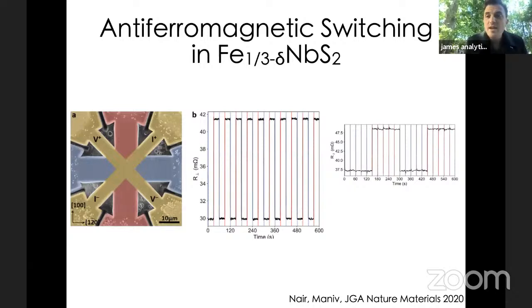What was kind of interesting, that is somewhat of a difference with these other systems, is that it didn't matter how low or high current we applied in these pulses. We always seemed to get a saturated resistance. In other words, we never saw the sawtooth-like structure. It was more like a telegraphing type structure that we saw, where after multiple blue pulses you just get one resistance, multiple red pulses, you just get one resistance, and so on. So this was a little bit different from the other systems in that sense.